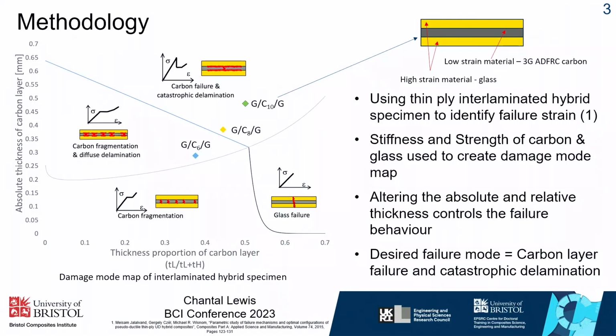The damage mode map was created using the failure stiffness and strength of the non-hybrid specimens and the carbon and glass. This was obtained by doing some tensile testing on those specimens. And so you can see here that to get the specimen design to fail in the desired failure region, the absolute thickness and the thickness ratio of the carbon and glass material needs to be varied carefully. Consequently, the design configuration that was chosen was 10 layers of the ADFRC carbon sandwiched between 2 layers of glass material.